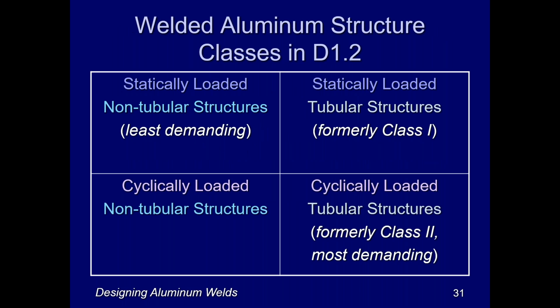Now, D1.2 also divides aluminum structures into one of 4 categories. And this little matrix here shows you what the determining factors are. But essentially, it comes down to, is the structure statically loaded or cyclically loaded? And by cyclically loaded, you can think of those structures that are subject to fatigue, for example, bridges. And then the other issue is, is the structure a tubular structure or a non-tubular structure? Now, when it comes to what's the most demanding and least demanding, statically loaded is easier than cyclic loaded, and non-tubular is easier than tubular, for a reason we'll see in a second here. And so statically loaded non-tubulars, those are the types of structures that are easiest to weld. Cyclically loaded tubular structures are the most difficult.